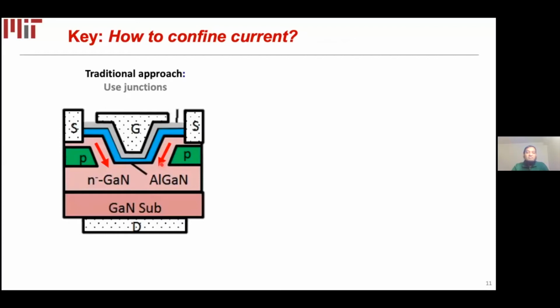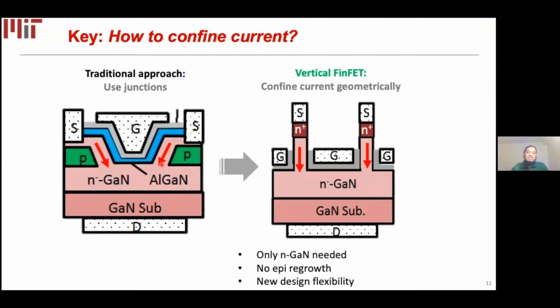However, there is a fundamental problem with this junction-based approach, because p-type doping of gallium nitride has proven to be very challenging, and this device architecture requires regrowth, and regrowth is very expensive and sometimes technologically challenging. To overcome these two problems, our group has come out with a new approach where, instead of developing a junction, we use geometric confinement and nanoscale patterning to control the carrier flow in a vertical transistor. So the beauty of this approach is we don't need any p-GaN and we don't need any regrowth. We can just take a simple epilayer structure with n-plus GaN, n-minus GaN, and a heavily doped GaN substrate, and just pattern it and make our transistors.